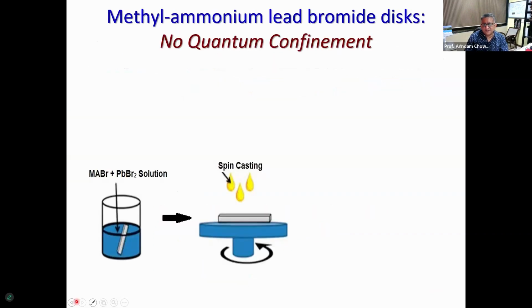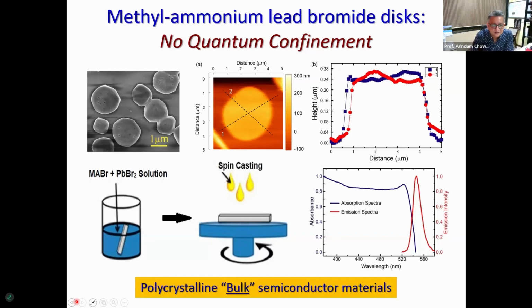And then it was very, very easy to make. You can take a little bit of a solution, put it on the surface and let it evaporate. You don't need to do too much heating and they will form these crystals. I am what I call a synthetically challenged chemist, so it is my students and Shaibal's students who did the synthesis. Once we created these crystals, we realized that again, they were bulk crystals, all right? They had very nice spectra, and these are bromides. There's no quantum confinement in these systems. And once we looked at these on our microscope, we started seeing something very funky.